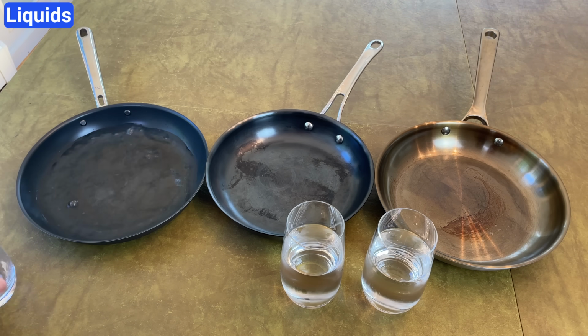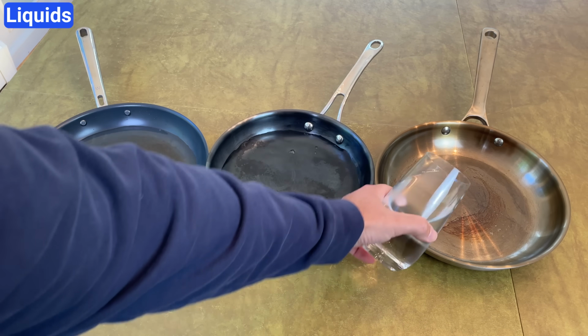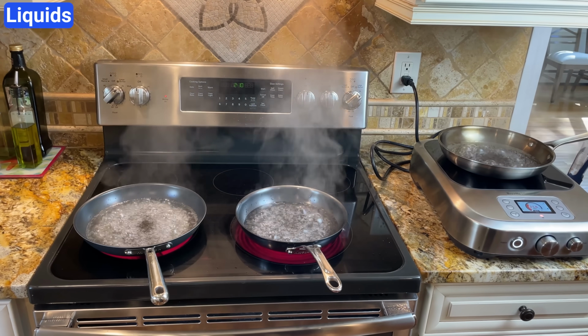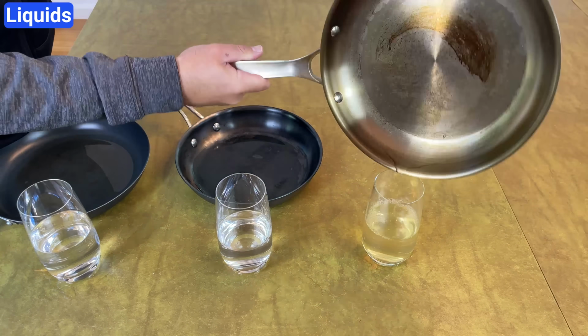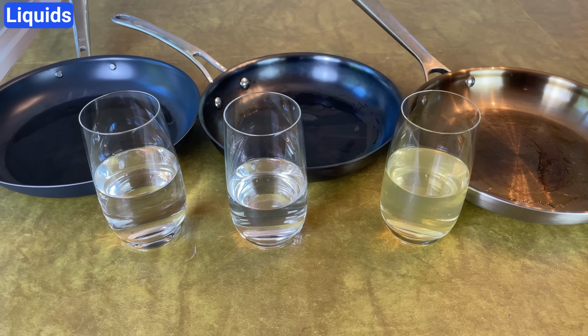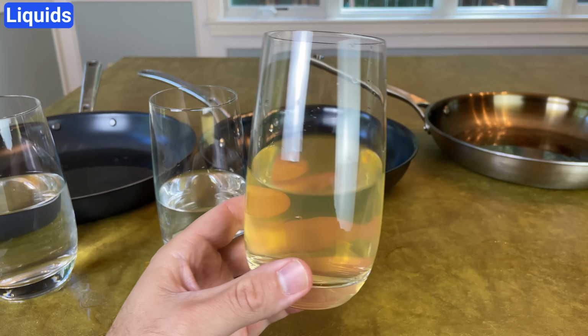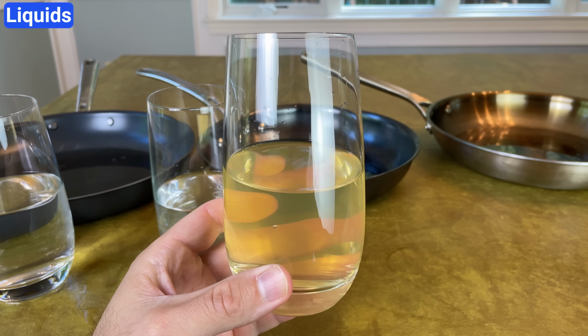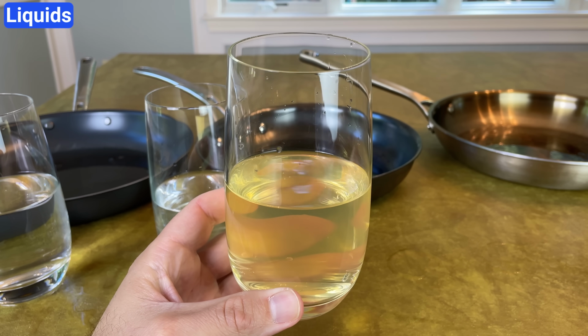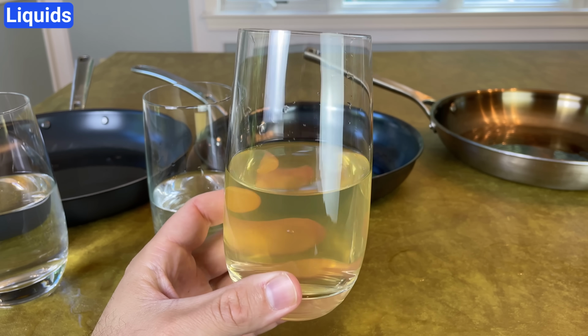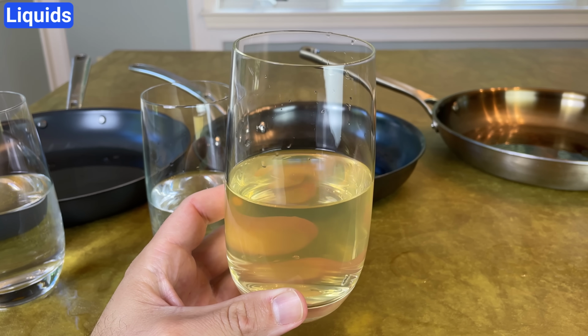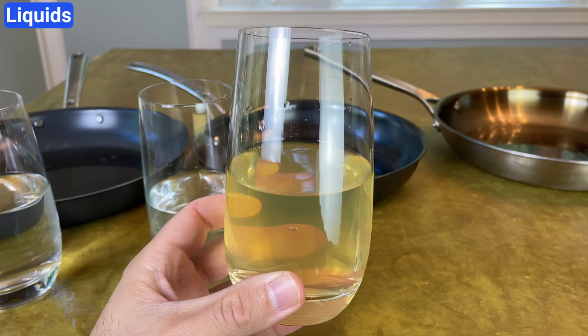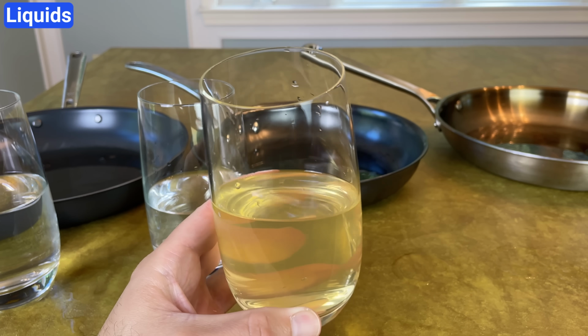To prove this point, I poured clean, filtered water into each pan, boiled them for 10 minutes, and then poured the water back into the glasses. The water from the Misen and Anolon came out completely clear, but the water from Strata was cloudy with a yellow tint, which means bits of the seasoning layer were breaking down and leaching into the liquid. This is normal for seasoned carbon steel or cast iron cookware, but it highlights another advantage of the nitrided surfaces